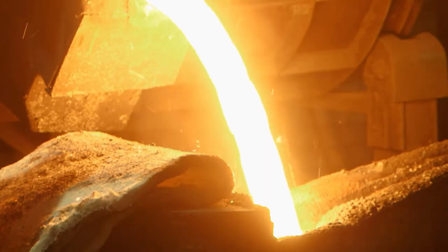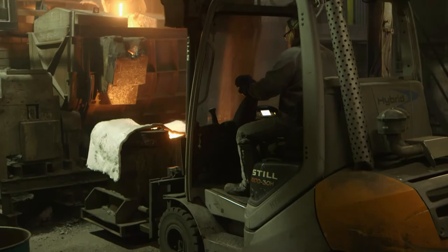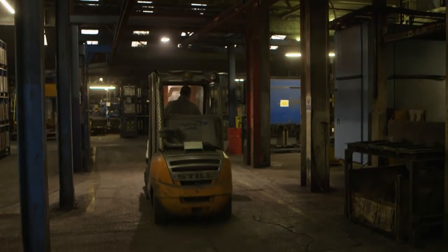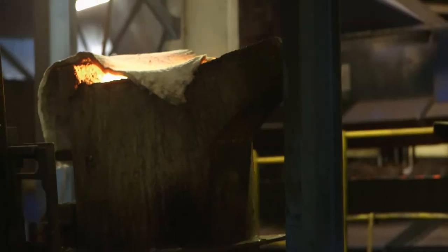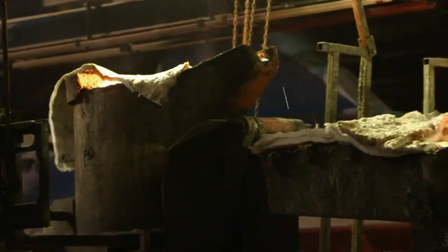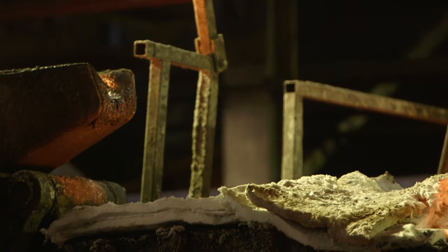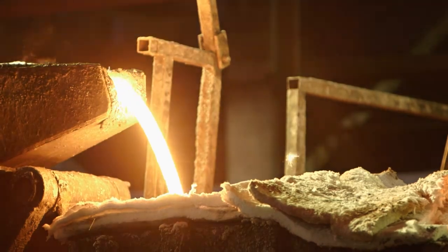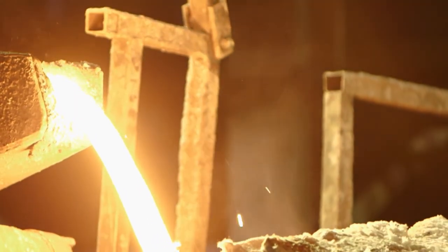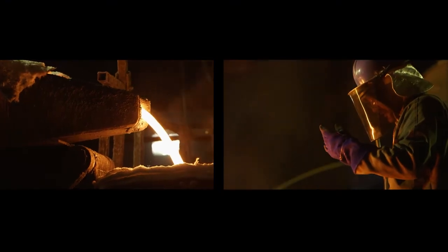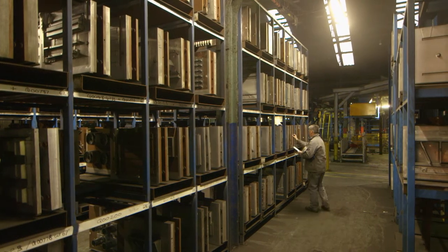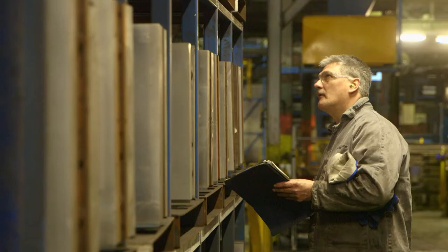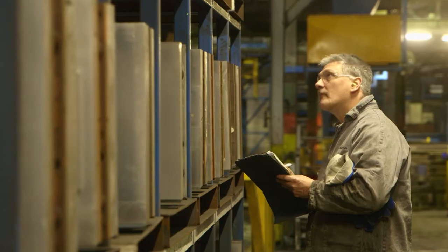Once melted, the molten iron is taken to two of the moulding lines, in a container or large ladle. The molten iron inside is still at a blistering temperature of 1400 degrees Celsius. The original challenge is getting the constituent parts cast together to produce the cast iron of which we're famous. Down at Coalbrookdale, it takes roughly 20 minutes to do all the castings in total for an oven.